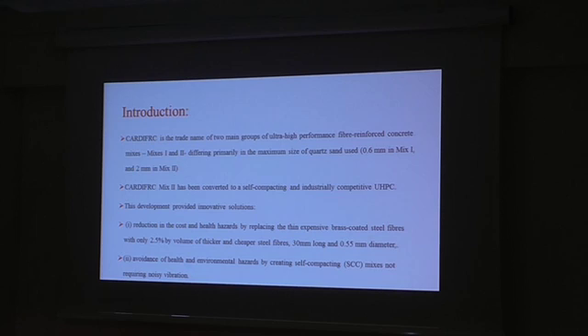CARDIFRC is the name of two main groups of ultra-high performance fiber-reinforced concrete: Mix 1 and Mix 2, differing primarily in maximum size of quartz sand, which is 0.6mm in Mix 1 and 2mm in Mix 2.